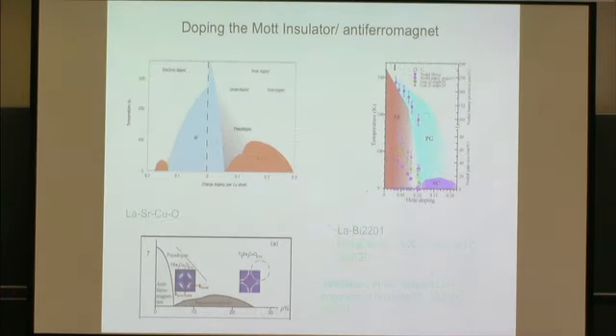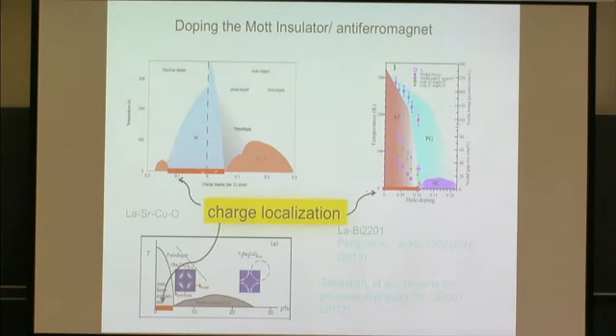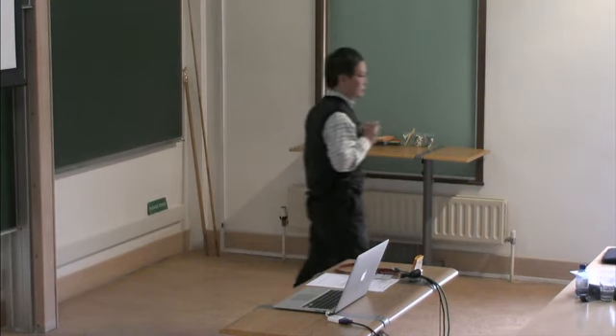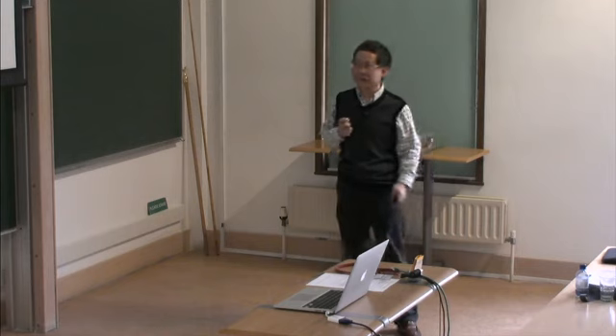So the question is, if you start from some well understood half filling, how do you dope this system? First, experimentally the charge is localized, which coincides with the long-range antiferromagnetic order phase. Then further doping will drive the system into the superconducting phase. At that point, antiferromagnetic long-range order is gone, but in the normal state, in the underdoped regime, you at least have pseudo-gap behaviors.